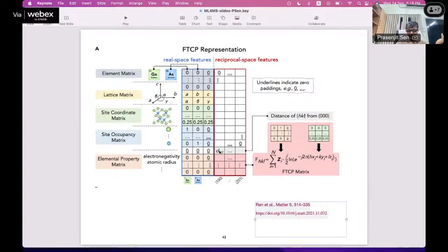And the line just above this, as I said, the last line of the site occupancy matrix, contains the lengths of these G vectors. So lengths of G vectors and the Fourier transforms of those elemental chemical quantities at those G vectors. So they had 59 columns here. Only 3 are shown, but they had 59 columns, each for a different G.